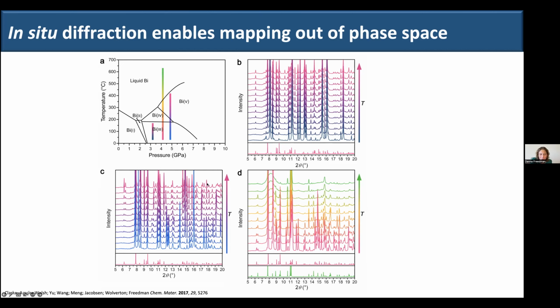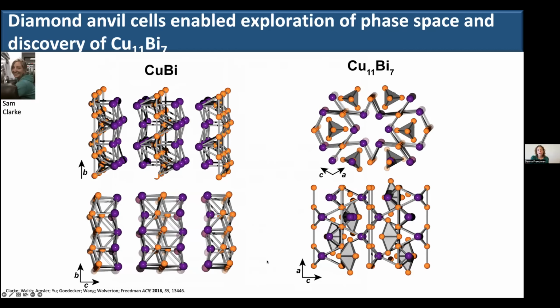Okay, so we have our powder patterns, and the patterns at the bottom, which should match the color at which they were found, denote 2 new bismuth copper structures. And so here we have, and this is work done by a former student of mine, Sam, who's now staff scientist at Livermore, still working with high pressure. So we have copper 11 bismuth 7, which is the first copper bismuth binary that was discovered. And this compound shows a lot of interesting structural motifs, which you could get into for hours, or well, I could get into for hours.